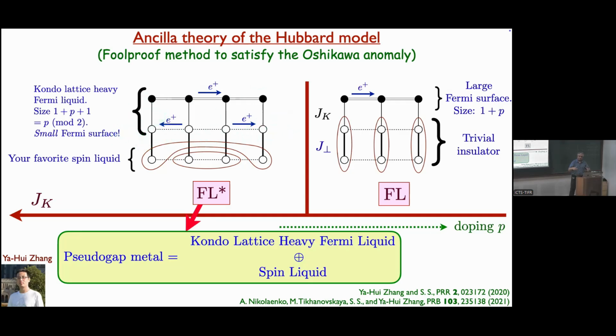So if you now form the large Fermi surface state of the Kondo lattice, the total number of holes here is 1 plus p plus 1, which is p mod 2. And everything is mod 2 because you can always take away a filled band. So you have a small Fermi surface, which is like the Kondo lattice heavy Fermi liquid because of the mod 2. So that's what you want, okay? Now this small Fermi surface obeys the Luttinger theorem for the Kondo lattice.